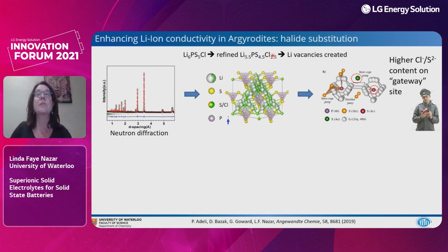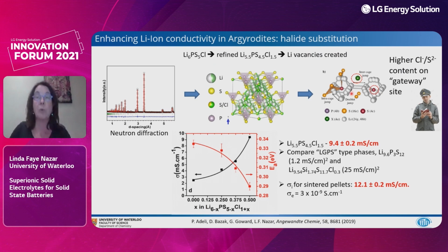But the benefit here is really just this: the weakened interaction of the lithium ion undergoing a hop with the monovalent anion now at that site, or more of it at least. And so again, the conductivity increases quite dramatically, up to almost 10 millisiemens per centimeter as the activation energy drops concomitantly. These values are of sort of 9, and for sintered pellets, not very practical, but nonetheless, values on the order of about 10 millisiemens per centimeter are fairly similar to LGPS phases that were reported recently by Ryoji Kanno and the group at Toyota. But this is a very easy material to make.